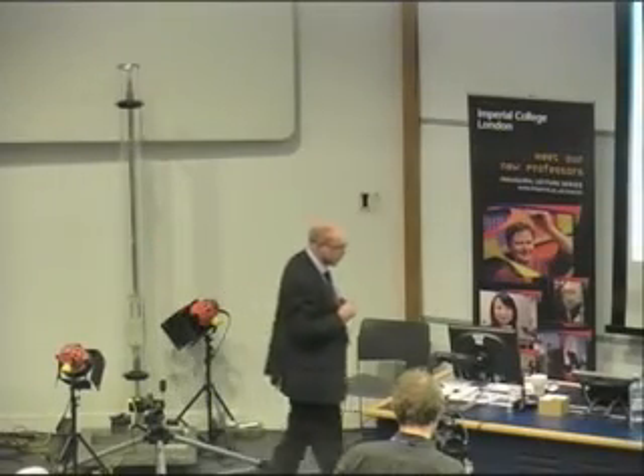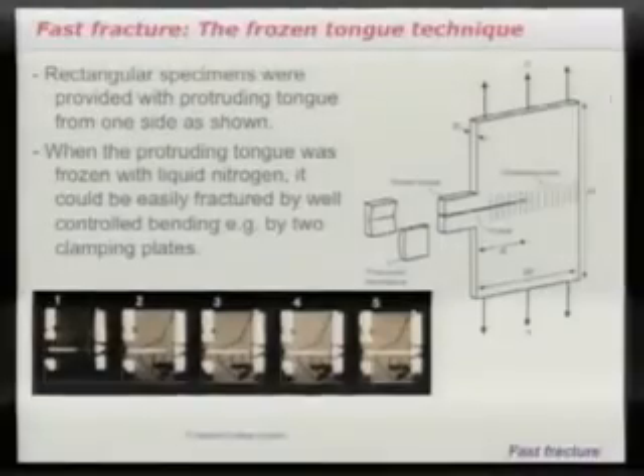And the principle of this is that you can preload these samples to different levels, but the polyethylene material, when you try to fracture it in the lab, it's actually remarkably difficult to fracture, because the crack tends to blunt out and you get tearing. And so what we did, we needed a way of initiating a crack.